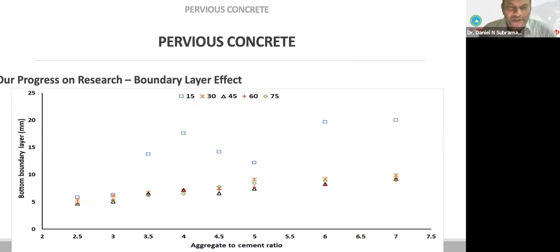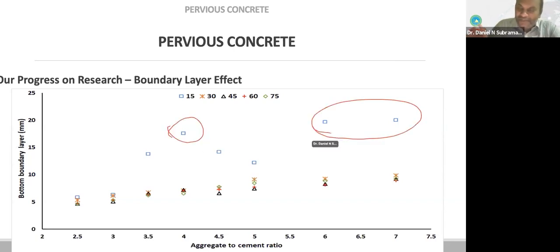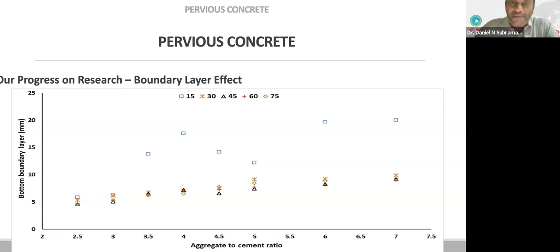Okay, now I think the one before last is the boundary layer effect. So as I said before, when you have the boundary layer, how much does the boundary layer affect, right? Now you can see one side, this is the bottom boundary, and the bottom boundary can go up to say around 20 millimeters. So now 20 millimeters is almost now in one layer. And if you have both layers together, out of 150 millimeters, about 50 millimeters gone in the boundary layer. So this is not acceptable in many cases. So when we are doing the laboratory study, we should be mindful about this boundary layer impact. But then one important factor that we noticed is also the compaction.